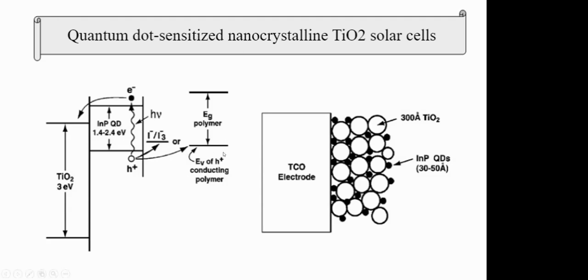Rest of the process is the same, but since you are using quantum dots, you need to find a different electrolyte, because the iodine iodide based one used with dyes cannot work as well. Most quantum dots integrated with solar cells are sulfur based, like cadmium sulfide and cadmium selenide, where iodine reacts with sulfur and selenium and degrades the quantum dots over a period of time.